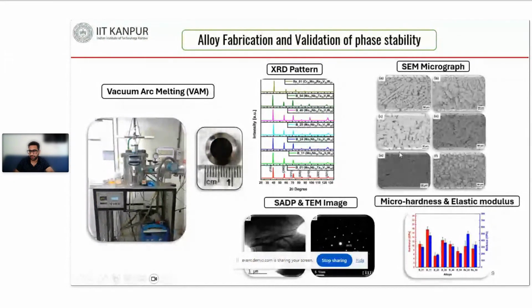Also in the micrograph in the SEM, they show a dendrite structure, but we do not see any traces of second phase particles. We have done TEM analysis, with bright field and the SAED pattern, and in the SAED pattern we got the reflections from a single BCC structure from the 111 zone axis, showing that it is a single phase structure.